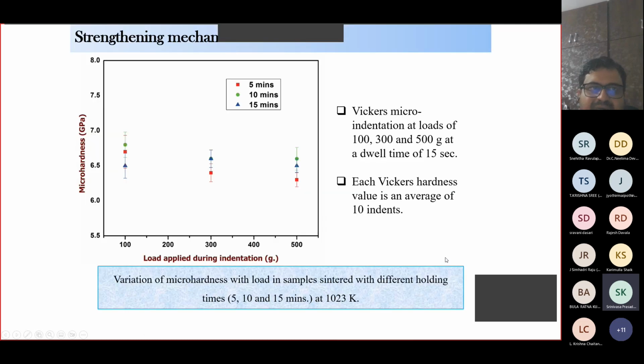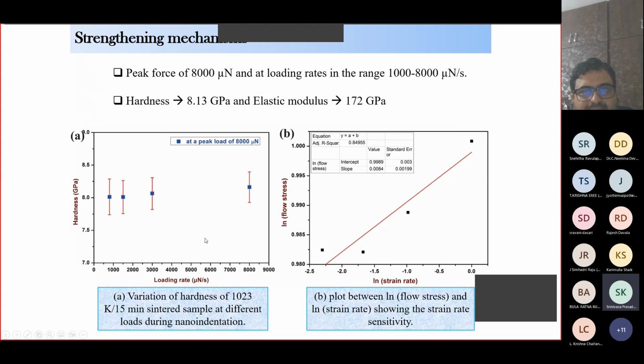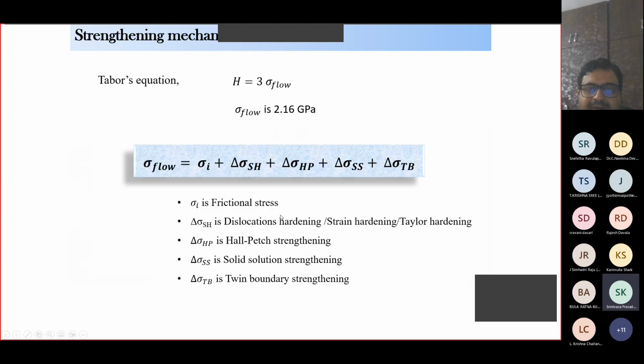And then when we measure the hardness of the samples at different indentation loads, we got about 6.4 gigapascals, and this is the best hardness that anyone has ever reported in this system. And then we also try to understand the strain rate sensitive behavior of this new nanostructured high entropy alloy, and it shows that the strain rate sensitivity is much lower in these alloys compared to the conventional dilute alloys. And also the activation volume is much lower.